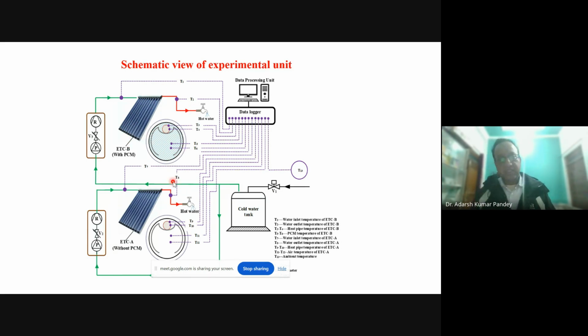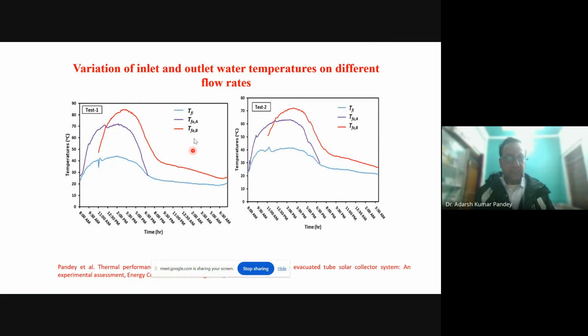And we tested it in the evening hours. In test one, you can see that even in the evening, after 5 o'clock, the water you are getting is more than around 40 degrees centigrade until 11 p.m. Especially for water for bathing and small kitchen applications, you need such a water temperature. We still tested until 6:30 a.m. Because of the phase change materials inserted into the tube, without acquiring any other space, you can supply heated water not only in the daytime but also in the nighttime.